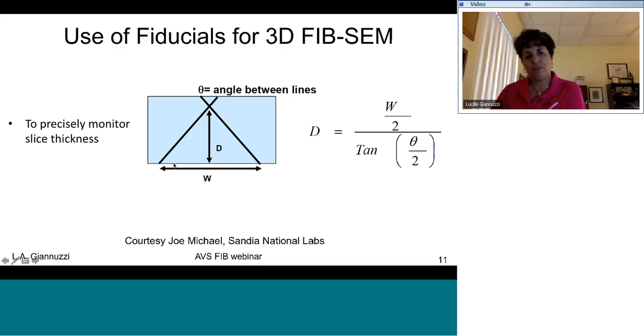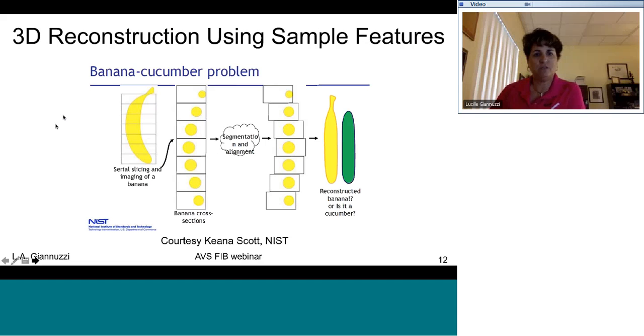And as you FIB mill through the structure, then obviously W is going to decrease, and that will also then, of course, decrease D. You can accurately determine what the slice thickness is instead of relying on the slice thickness that you set into the software. Reconstructing and spending probably for every hour of instrument time, there can be up to 10 hours or more in doing the reconstruction. And this is also often the difficult time. Not only just the reconstruction, but if you want to do any sort of segmentation and analysis, this can take a significant portion of the time.